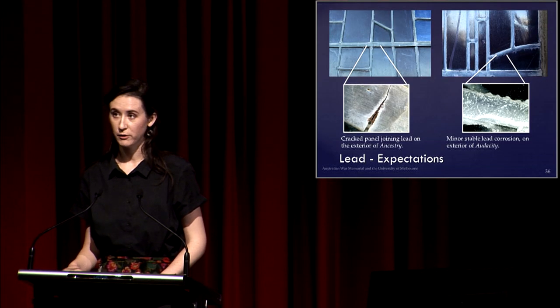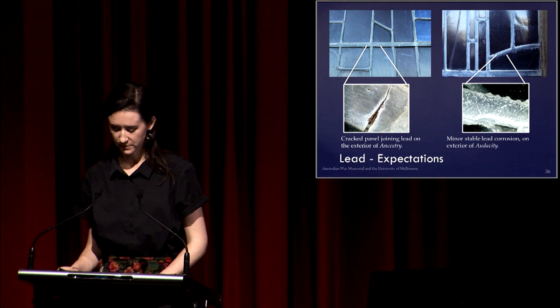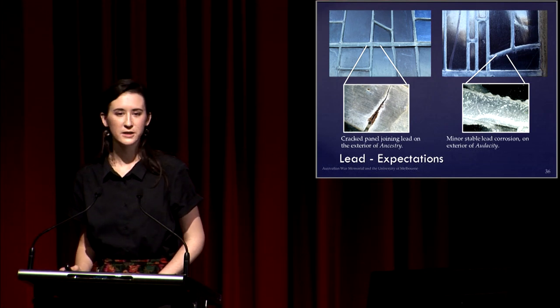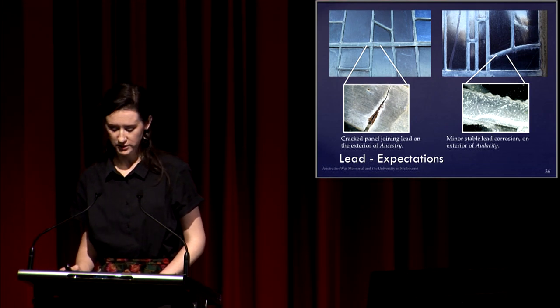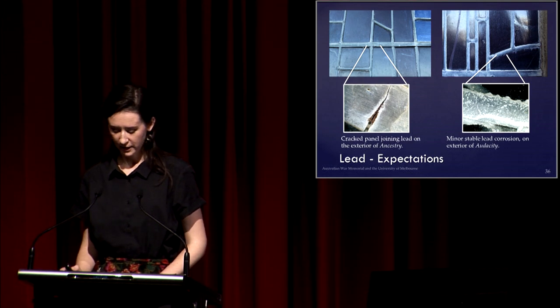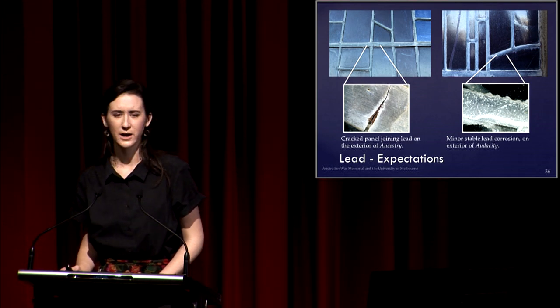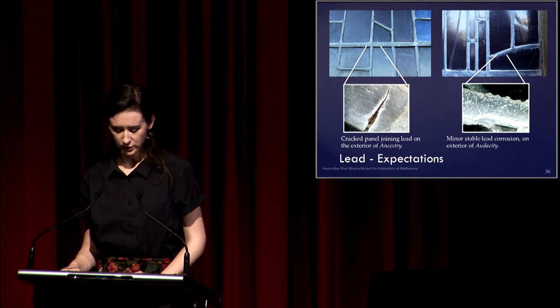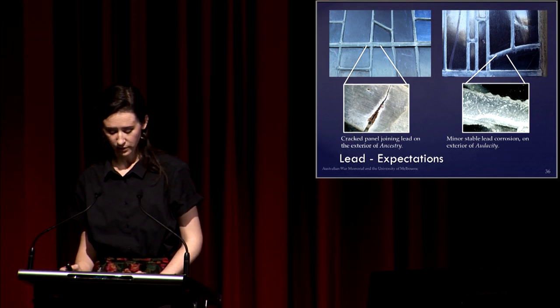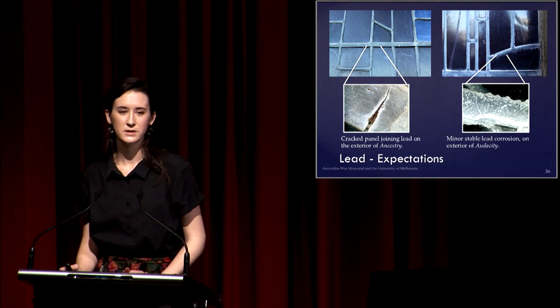The lead cames are vulnerable to damage caused by thermal expansion and contraction, as well as physical forces such as wind, vibration, building movement, and impacts that fatigue the lead, causing cracking and weakening. Corrosion may also occur as a result of exposure to water and pollutants, such as deterioration of adjacent glass, as well as galvanic corrosion caused by contact with other metals that were used in the windows.